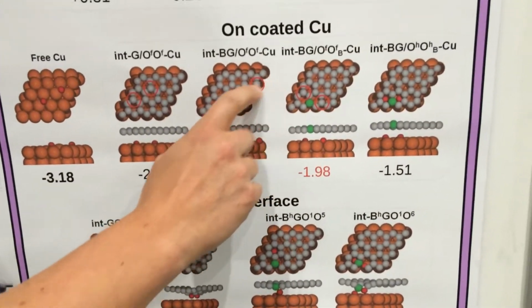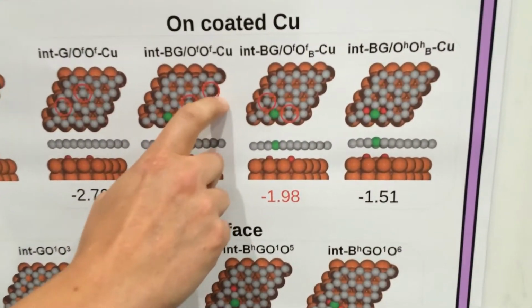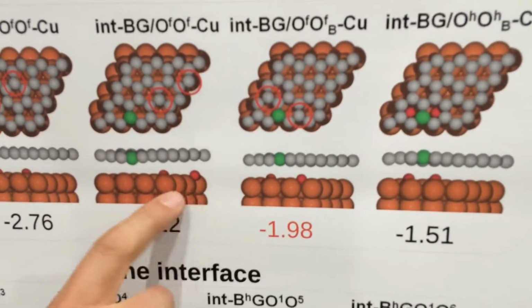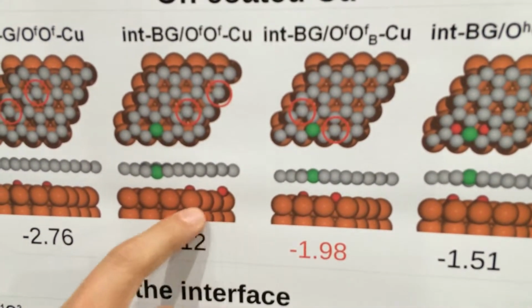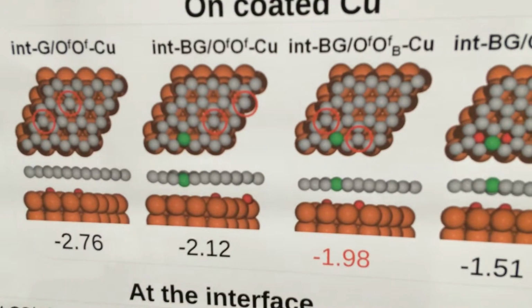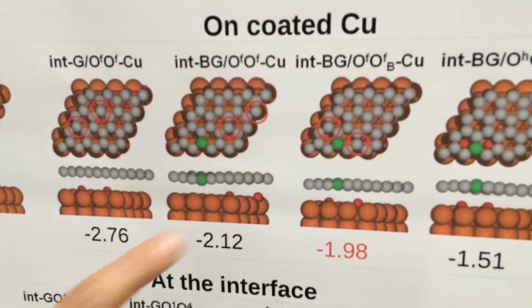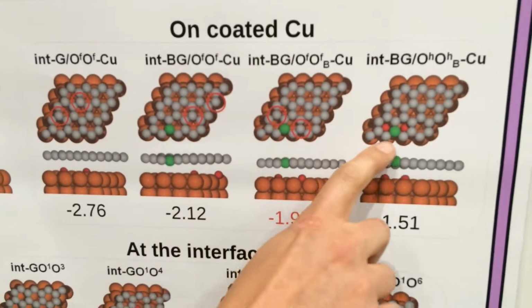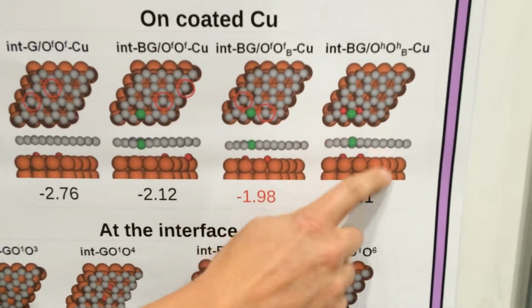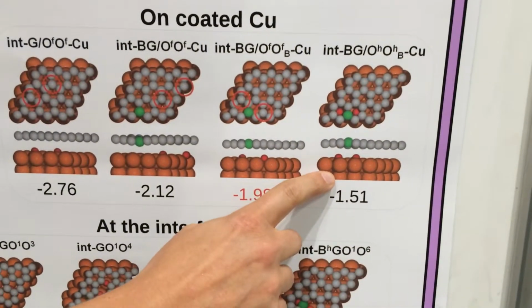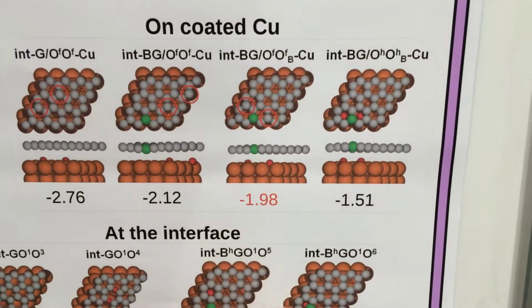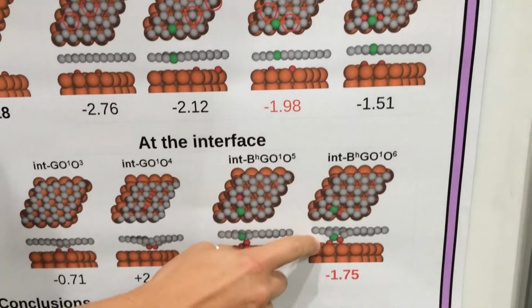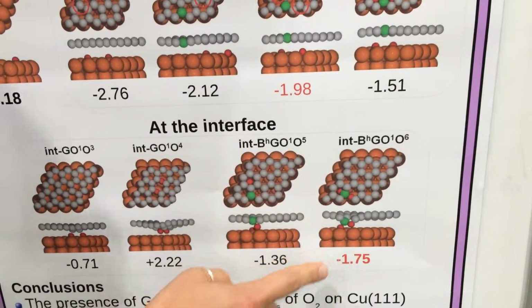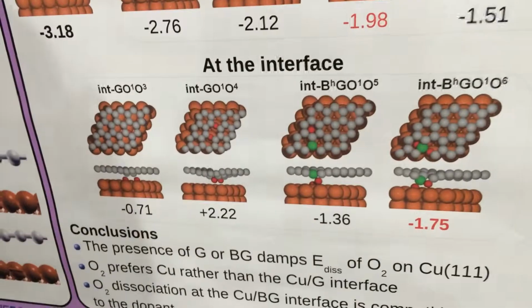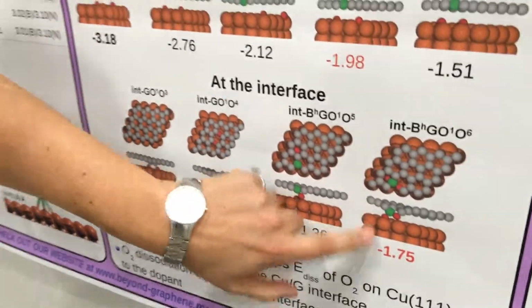Once you are with the oxygen away from the boron dopant, then you would rather dissociate on the metal than at the interface. But when you get closer and closer to the dopant, then you have a situation where oxygen dissociates on the copper, but also a situation where oxygen dissociates at the interface, close to the dopant, and in this case the situation is preferred.